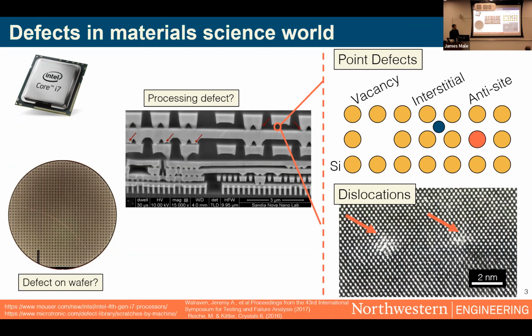I'm also going to touch on dislocations, which are quite a bit harder to show in some really simple schematic like this. But here we're looking at silicon atoms, and you see near a dislocation, you essentially have a boundary across which the arrangement of the silicon atoms changes. So dislocations are kind of like a line of defects that disrupts the crystalline structure.